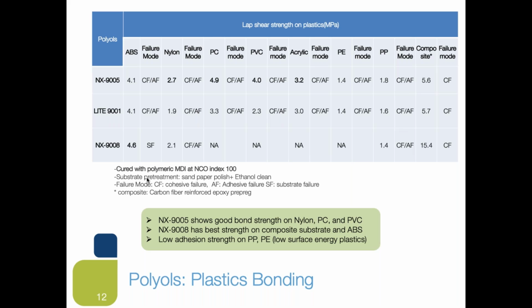So overall, NX9005 has shown good bond strength on nylon, PC and PVC. NX9008 has shown the best strength on a composite substrate and ABS. However, on the polyolefins like polyethylene and polypropylene, we have seen low adhesion strength due to the low surface energy of those types of plastics.